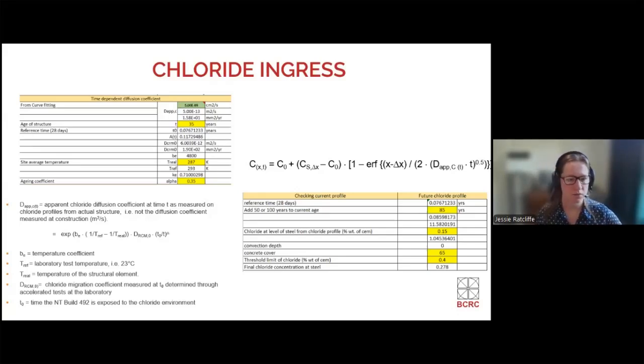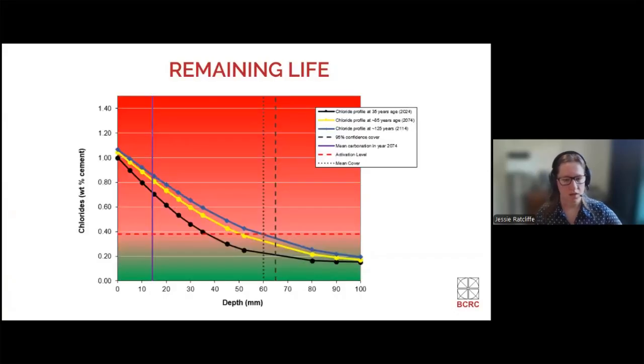And we finally get to our final plot. So we have a plot of our current chloride levels, so heading towards the reinforcement cover being represented by the vertical dotted lines. That's our average and characteristic covers. You can see initially we're nowhere near our critical level of 0.4 weight percent of cement. However, after 50 years, that's our yellow line, we are getting pretty close.